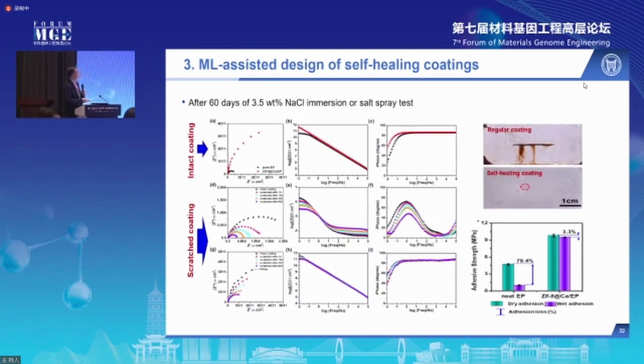And this is showing the performance of the coating after 60 days of immersion in chloride solution. Basically, the best performer, once it's scratched, quickly heals, and the performance can be literally the same as the intact coating as well. And also, this is for the salt spray test, 60 days, and nothing really occurred in the coating scratch.